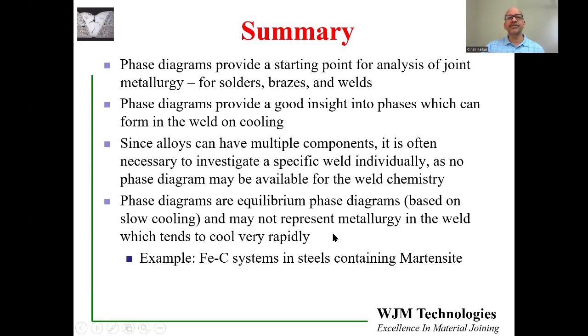So it does happen that there are situations where the phases might be sluggish, or they might transform into a phase which is not familiar or not occurring on the phase diagram. An example is the iron-carbon phase diagram, which all the steels are based on. Steels can produce a phase, not on the phase diagram, called martensite, which occurs only due to rapid cooling. So keep in mind that phase diagrams are a great place to start your analysis if you're trying to understand a particular weld. But there are a lot of exceptions because of the alloying and because of the cooling rate, where what you get in the weld might be a bit different or sometimes a lot different than what you get on the phase diagram. So this is a great starting point, but do not stop there. Conduct metallurgical analysis and mechanical testing before you draw any conclusions.